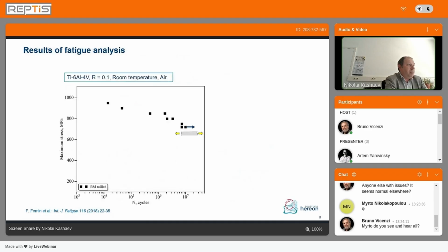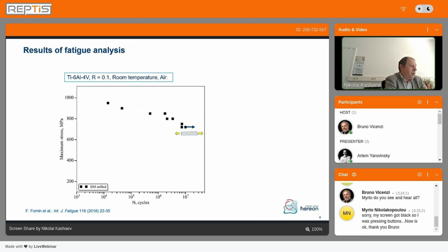If we are performing testing of titanium, for example, as a sheet material, we have that kind of fatigue results represented as a Wöhler curve. It means maximum stress of the cyclic loading versus the number of loading cycles until failure. If we compare the behavior with the weld in a welded condition, you see we have a significant reduction in fatigue strength, both for finite fatigue life and for infinite fatigue strength level.